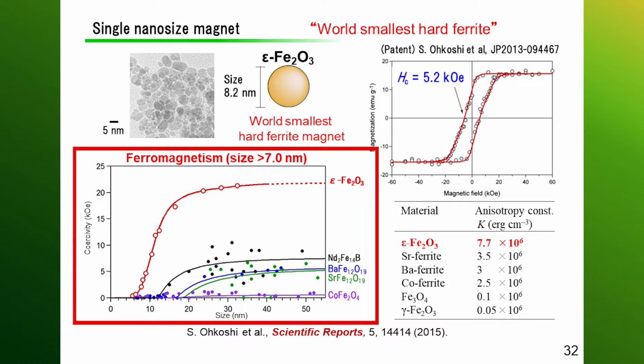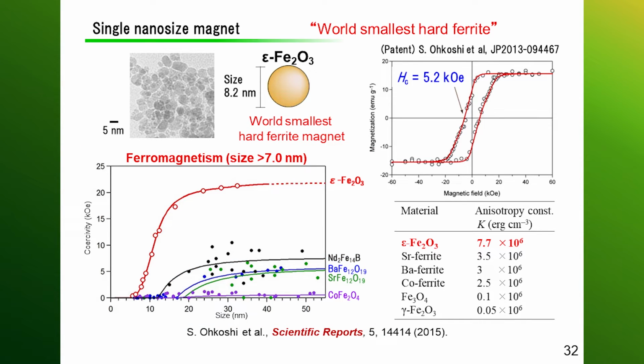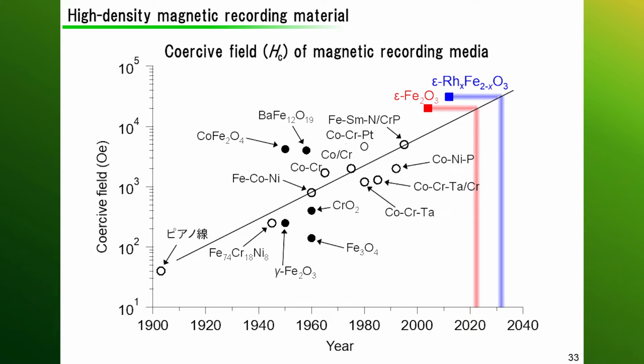achieving 5 kilo-Ørsted even at 7.5 nanometers. In the case of rare earth magnets like neodymium iron boron, coercivity is lost when the size falls below 27 nanometers. Changes made in the crystal structure enabled the simple iron oxide capable of maintaining a high level of coercivity in a small size, and indeed, this was the discovery of the world's smallest hard ferrite.